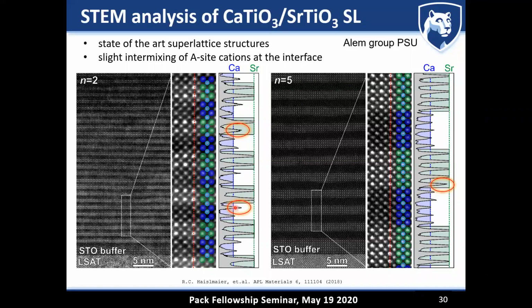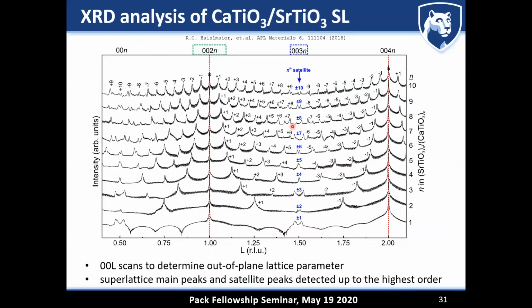In fact, if you do X-ray diffraction, you can very precisely characterize the amount of intermixing. And I'm just flashing here the in-depth X-ray analysis that we've taken on these calcium titanate, strontium titanate superlattices. And so there's a few exciting things here. The most exciting thing is that if you have a very good overall periodicity over the superlattice structure, you would expect to see the satellite peaks in X-ray diffraction that are arising from the superlattice structure. You should see them all the way up to the highest order. And in fact, what we show here is that we achieved this in this complex oxide stack.